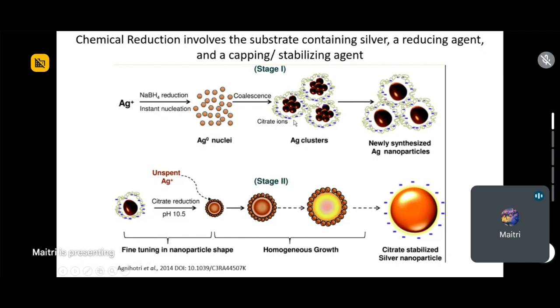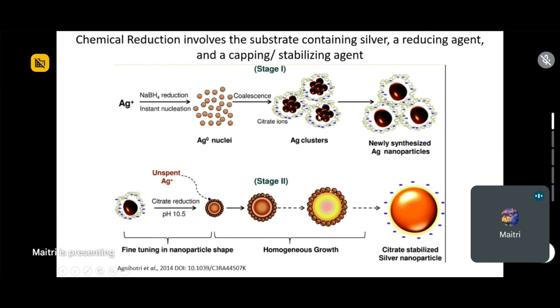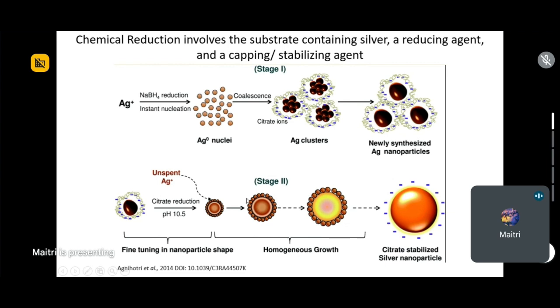Now, these Ag clusters will immediately be capped by something called a capping or a stabilizing agent, which in this case is citrate or trisodium citrate. These newly synthesized nanoparticles will rearrange themselves. Here, the clusters are just like literally that, just clusters, like cluster of grapes or something. But then they just rearrange themselves to form a proper sphere. And then these nanoparticles will undergo further reduction by the citrate molecules, and they will just form a better structure. They will fine tune themselves into a proper structure such that it goes and undergoes stages of nucleation to finally form this big silver nanoparticle stabilized by citrate molecules. And this will be normally a size of 20 to 50 nanometer. So these will be very small, which undergo so many stages of condensation and nucleation to form a 20 to 50 nanometer sized silver nanoparticle.